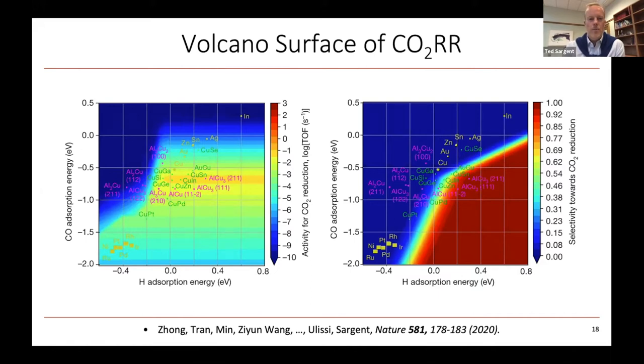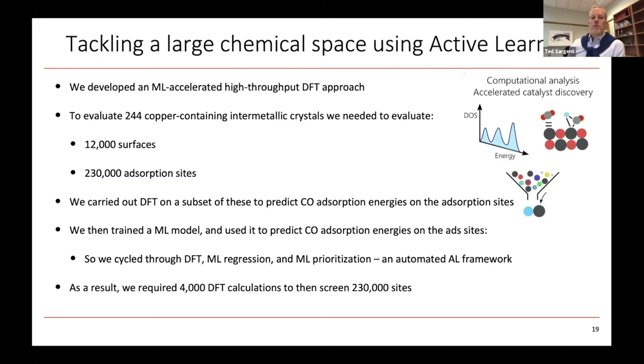Now, it turns out that if you consider all 244 copper containing intermetallic crystals, but then you look at all the surfaces and you look at all the adsorption sites, you do have about 230,000 potential calculations on the adsorption sites to develop. And that is very computationally demanding, even with pretty good access to high performance computing. That was kind of beyond the scope of what we could do.